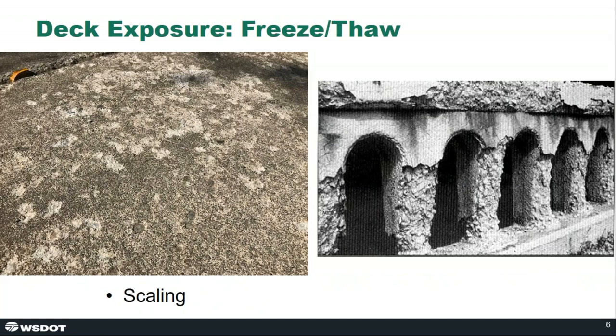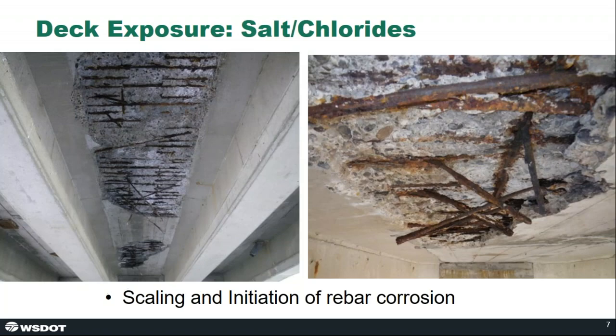Next is freeze-thaw damage. This is caused by water expanding within the capillary pores of the concrete and leading to scaling and material loss. The photos here show that sort of deterioration on a sidewalk and a bridge barrier. Salt and chloride exposure is also a major concern. The salts worsen the scaling due to freeze-thaw at the surface of the concrete, but of greater interest is the fact that when chlorides permeate down to the level of reinforcement in the bridge decks, they lead to the initiation of corrosion and spalling.